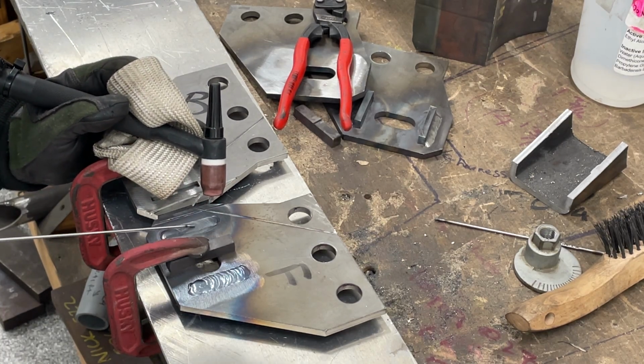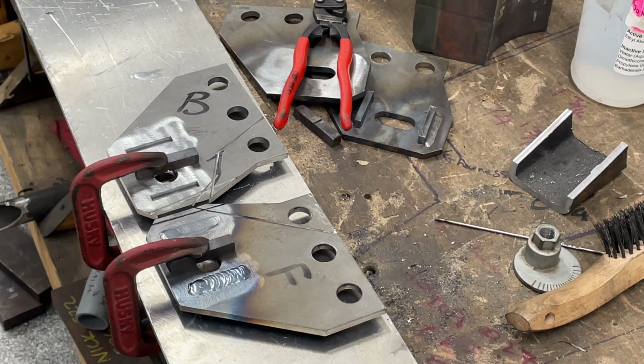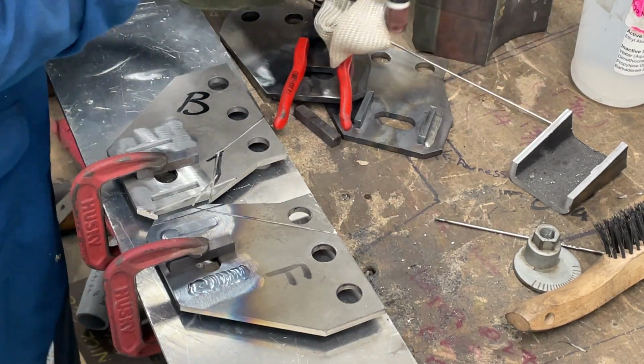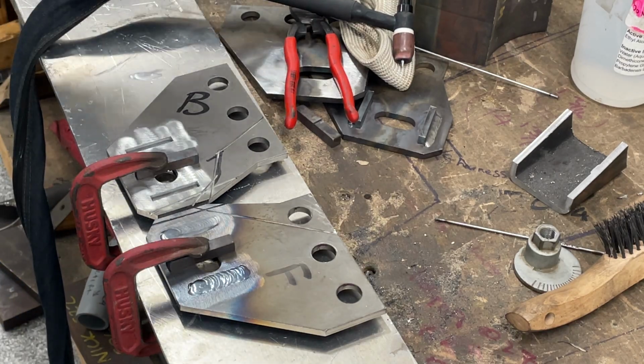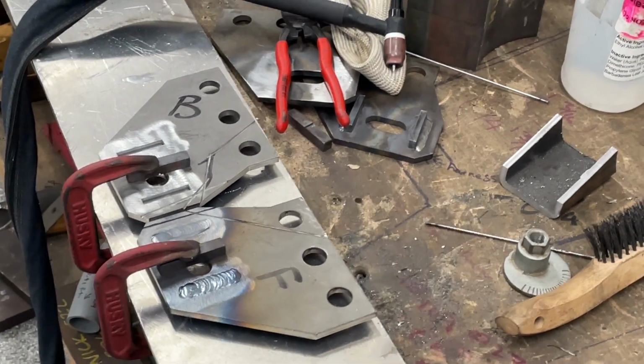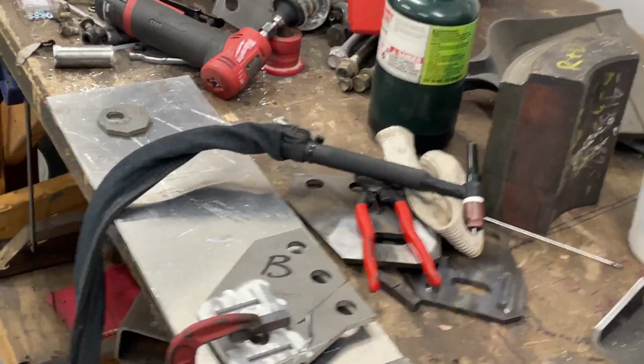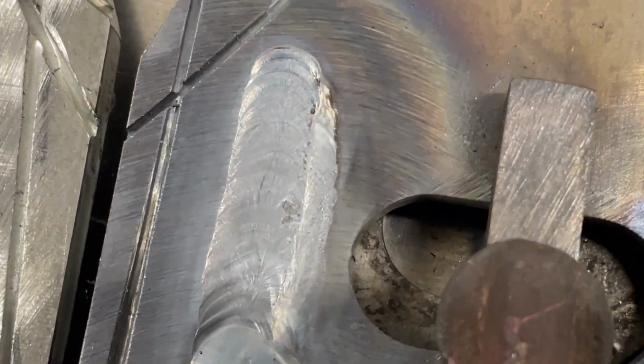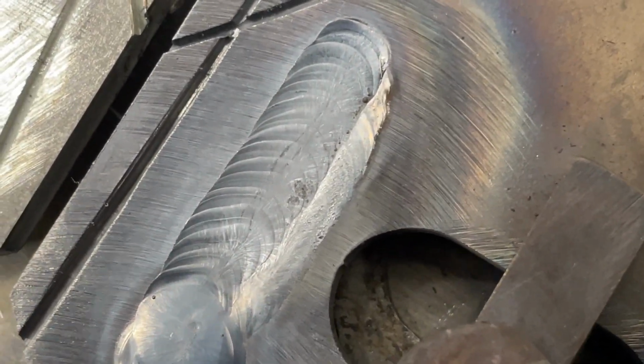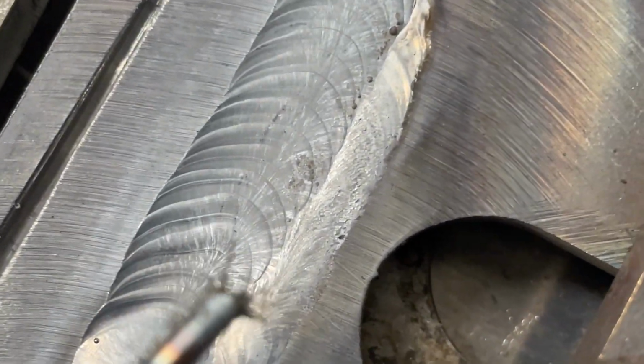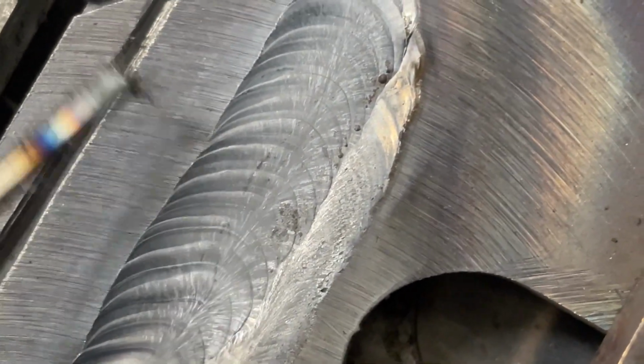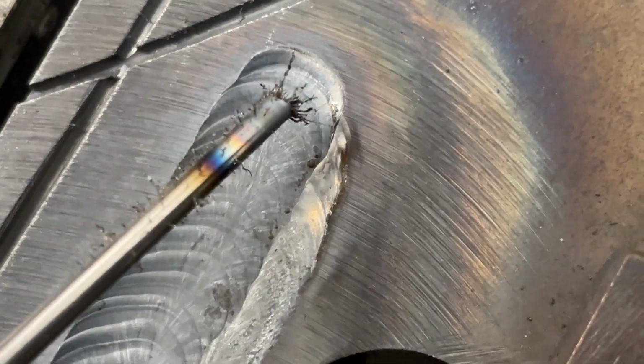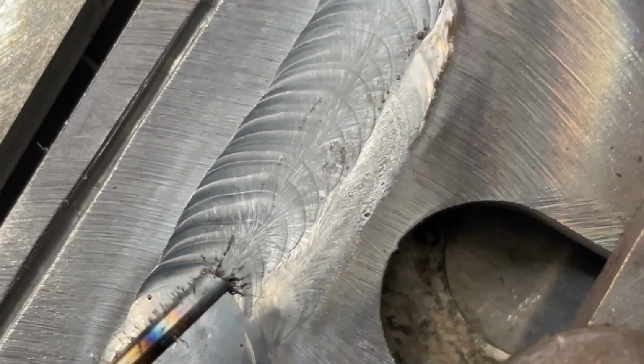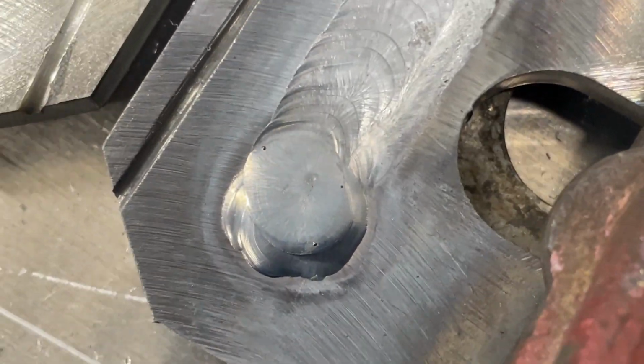Ooh, that epitaxial grain growth is really pretty. Let me show you what that looks like. Welds solidify and they have grains. So if you're lucky and you've welded well, you can actually see a reverse chevron-like shape here. You see how it's going that way versus the weld puddle? That is the material solidifying and showing off its grain structure. That is beautiful.